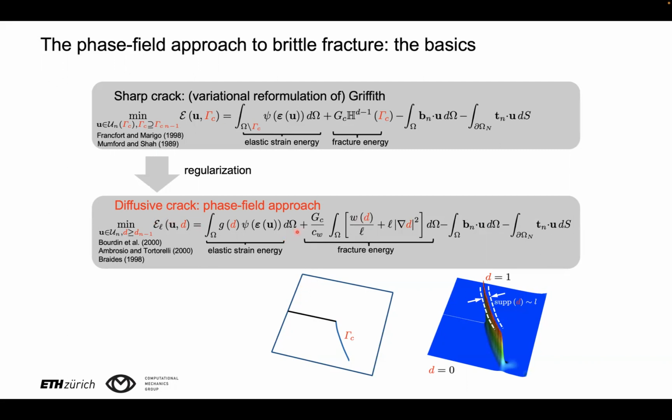And so it is the minimization of this functional which will give us our governing equations, which, once solved, will give us the field of the damage, and this will then show us immediately where the cracks are propagating and how. This minimization is again a constrained minimization, because, to be sure that cracks cannot heal, we have to make sure that d can only increase.